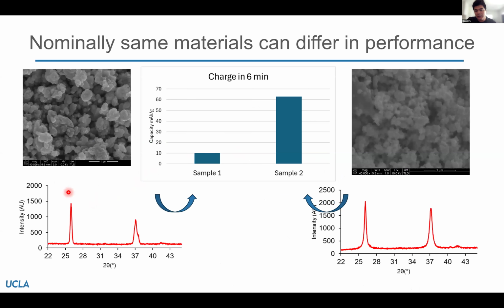But even within the same solid solution, so if we have notionally the same solid solution, we put in the same materials, we make them under very similar conditions. They index to the same crystal structure, as I'm showing with these powder X-ray diffraction patterns. They have roughly the same secondary particle size, which are known in the battery literature to affect charging and discharging